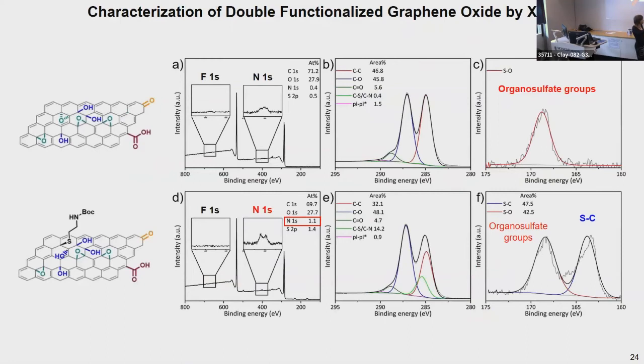So, regarding XPS, this is the survey of the starting graphene oxide. And when we look at the S2P area, there is one peak assigned to the organosulfate groups, because there are organosulfates on the surface of graphene oxide present in a low amount. After the first reaction, so after the epoxide ring opening, we could see the appearance of nitrogen. And looking at the S2P area, there was a second peak appearing assigned to the S-C bond, so confirming the occurrence of the reaction.